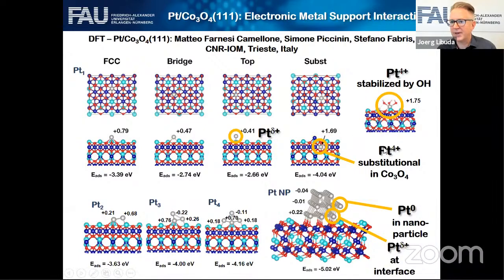You can also find platinum four species, and you can make them either by stabilizing the platinum four by OH or water ligands. That's very similar to the species I showed before with the cobalt. Or you can make this platinum four by embedding the platinum in the lattice. Yeah, and if you embed the platinum in the lattice, you will eject some cobalt ions from the lattice. I come back to that in a minute.